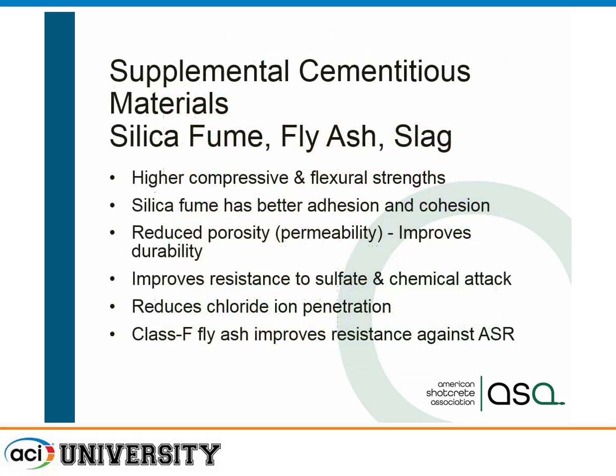We can also add things like corrosion inhibitors. We can use a variety of supplemental cementitious materials. Silica fume is obviously one of our popular ones. Anybody here use silica fume in concrete? You found it was very thirsty, right? Sucked up a lot of water. You really have to get water on it quick. But it also makes it sticky, so it'll stick better when we're shooting overhead. And it also allows us to shoot thicker layers. So if you have a repair that's 3 or 4 or 5 inches thick, we can do it in one layer if we're using silica fume because it holds together.